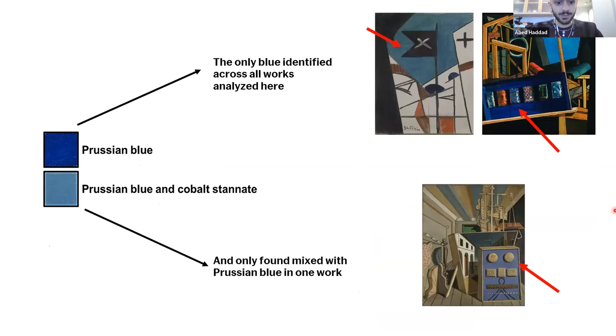And finally, for the blues, de Chirico lists a few blues. Some are clearly identifiable, like Prussian blue or ultramarine. Others are less so, such as mineral blue or cerulean blue, which can denote cobalt stannate or other mixtures that produce a cerulean hue. So here, the predominant blue used by de Chirico across all time periods is Prussian blue, and it was found both in the Vera Falsi as well as the authentic metaphysical works. And while the blue box here in the Faithful Servitor appears very dark and a very deep Prussian blue, the box in Biscuits actually contained both Prussian blue and cobalt stannate. So it's interesting to see him mixing these two blues to come up with this much lighter hue.